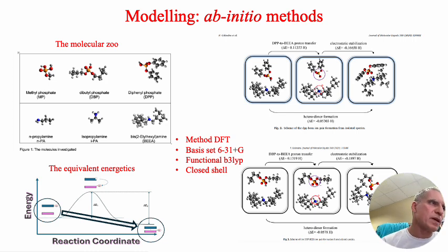As a scheme, we can say that a guy gives the proton, but this process is not spontaneous because it requires energy. But then the stabilization of these two species, making a compact complex, stabilizes the overall energy. So the overall process is spontaneous.